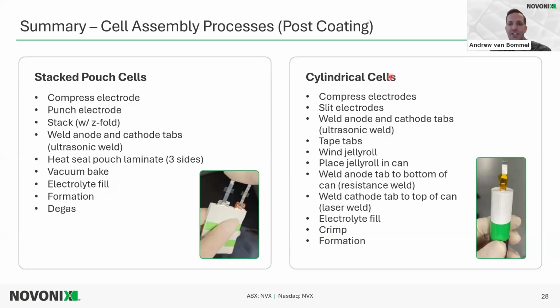In cylindrical cells, the electrodes are compressed in the same way. The electrodes are slit down web, and that width is the height of the electrodes in the jelly roll. Then the anode and the cathode tabs are welded. So the electrodes again are patch coated so that the uncoated area will have the area so the anode and cathode tabs can be welded on. The tabs are taped to prevent any shorts.